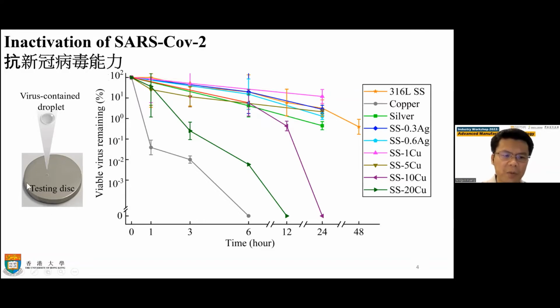And this is a sample. How we do the testing is, we make a droplet. This is a virus-containing droplet, and then we drop it onto the surface, just to simulate the contamination. When you're speaking or coughing, you have droplets dropping on the surface.